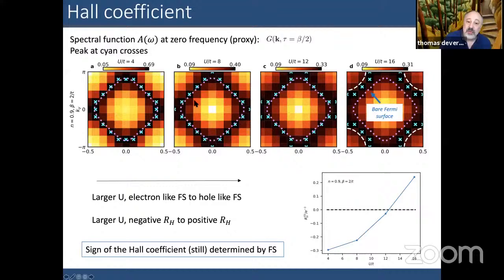So if you look as U changes, going from being centered around zero, zero to being centered around pi, pi, the point at which that Fermi surface changes its topology is exactly the point where the Hall coefficient changes its sign. So even though we have a very bad metal, strange metal, whatever you would like to call it, at very large values of U, this way of thinking in terms of the Fermi surface seems to hold up: the topology of the Fermi surface gives us a good way of determining at least the sign of the Hall coefficient.